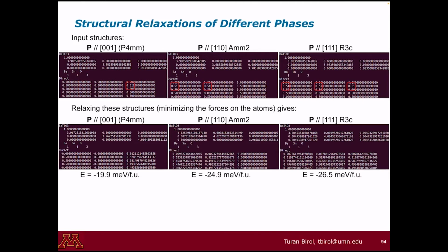So what this tells me is I cannot make very solid predictions because, again, this is a zero temperature calculation. But I won't be too surprised that if I increase the temperature well above room temperature, due to the entropy, essentially just due to the temperature, kBT, I will have so much disturbance in my system that this ferroelectric displacement, this coherent displacement, will disappear, and I will have a cubic crystal structure, which is what's observed.